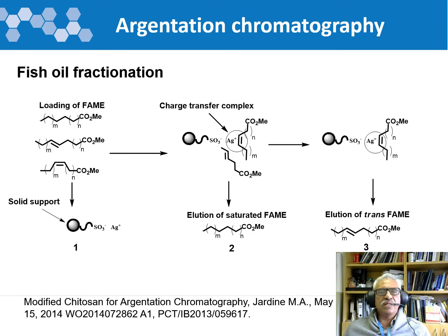And then this is the argentation. Argentation is basically you take your polymer, put sulfonate groups on there, and then you load it with silver. So chitosan served that purpose well. And then if you pass through a mixture of fish oil, for example, these oils have saturated and unsaturated fatty acids. So the unsaturated fatty acids will be retarded by complexing with the silver, and the more saturated ones will move faster. So one can get very good separation of saturated, which is cosmetically more useful, versus the unsaturated ones, which can be used as antioxidants for nutraceutical purposes.